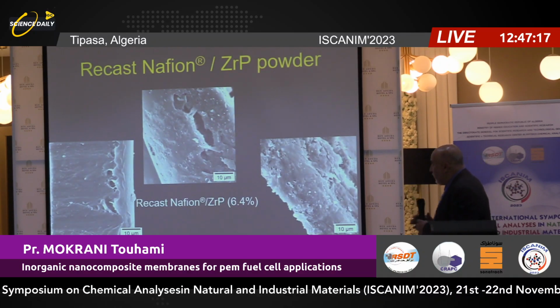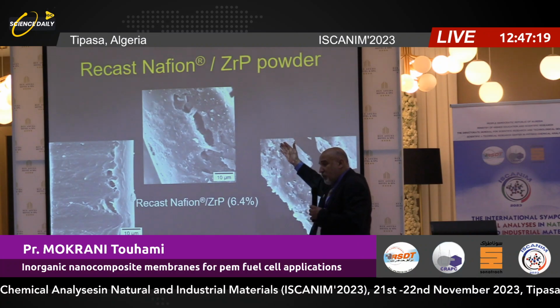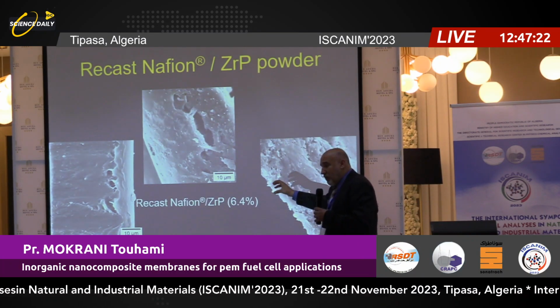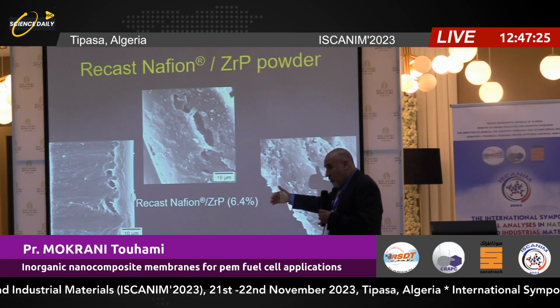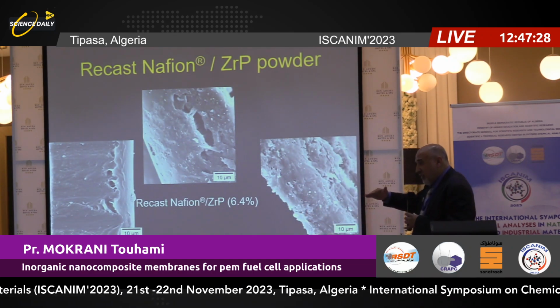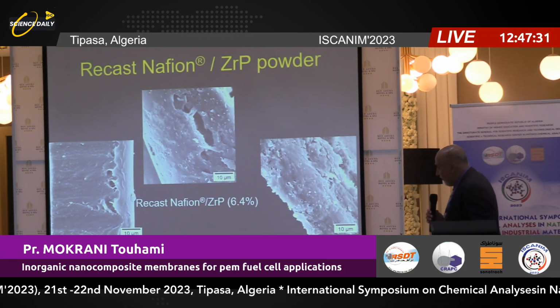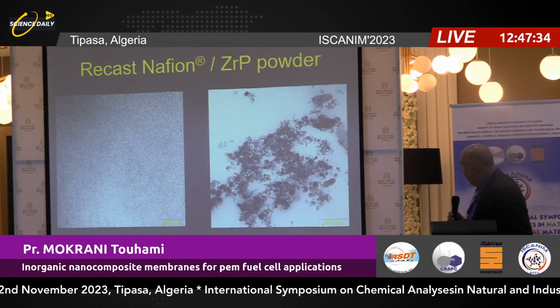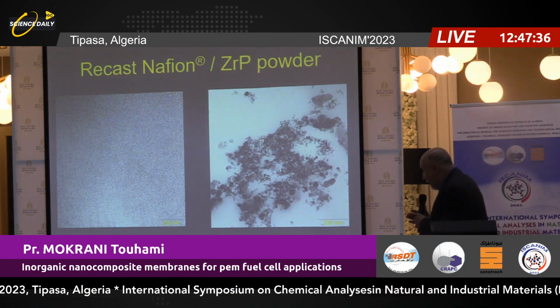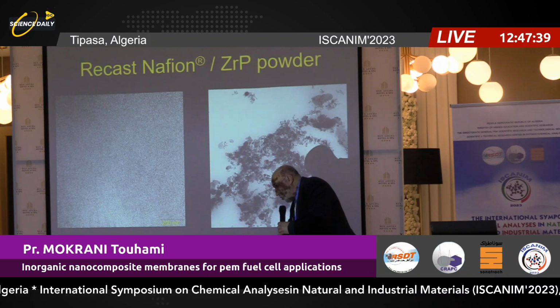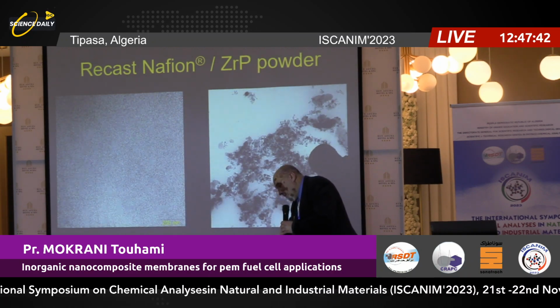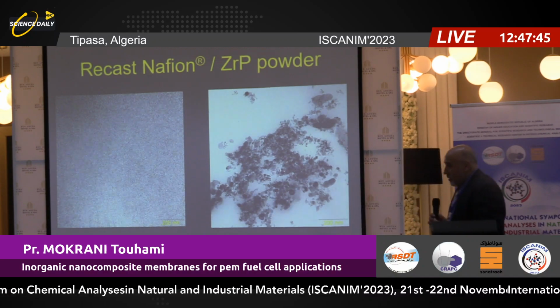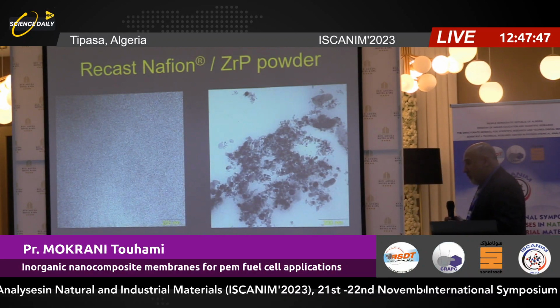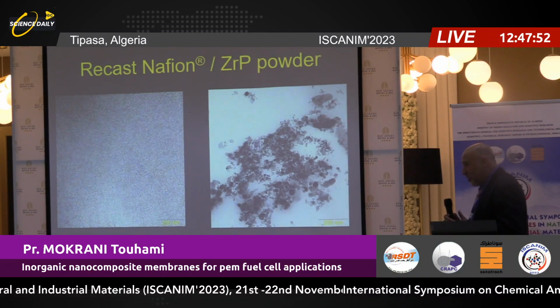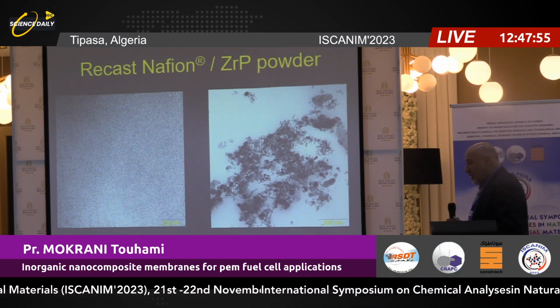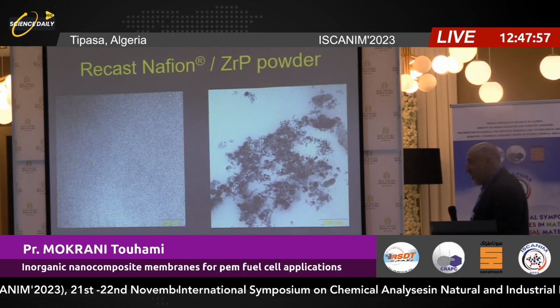This one is very important because Nafion is a proton conductor, zirconium phosphate is a proton conductor. So when we put them together, we increase the conductivity of Nafion. So the nanocomposite material is better than the pristine film. So in this case, you can see we reduce it to 12 nanometers. Especially zirconium phosphate, the higher the surface area, because it's a surface conductor, the better. And the smaller the size, the higher the surface area.